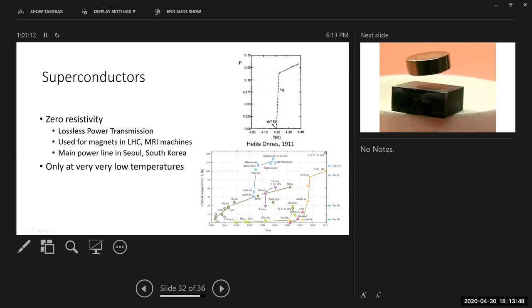And this is why you don't see superconductors everywhere. This is why your iPhone does not have superconductors inside of it, because cooling things down is expensive. The threshold temperature here is 77 Kelvin, because 77 Kelvin is the temperature of liquid nitrogen. And you can buy liquid nitrogen in a store. It's cheap. If you can cool things down with liquid nitrogen, that's cheap. At lower temperatures, you need liquid helium. Liquid helium is very, very expensive. So MRI machines use these YBCOs, yttrium barium copper oxide, which work at liquid nitrogen temperatures in order to superconduct.